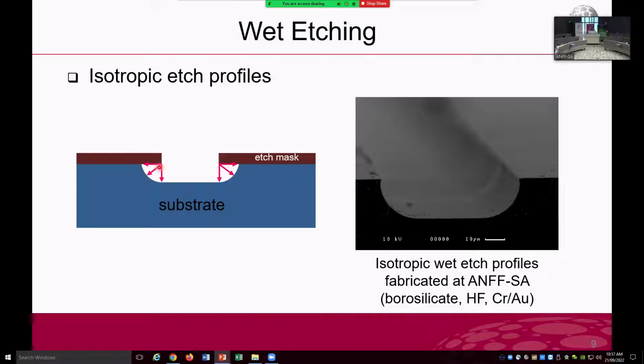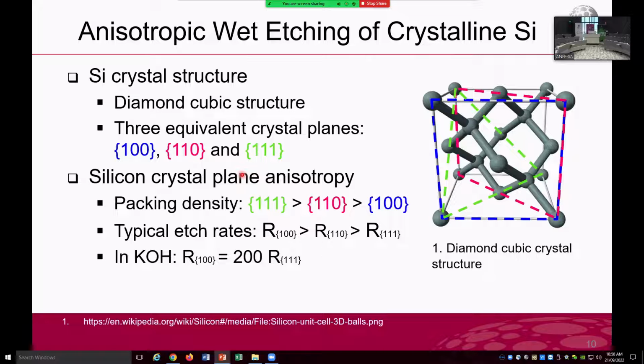As you see, in isotropic wet etching, the etch front proceeds as a spherical wave, so etch rates are equal in all directions, horizontal and vertical. And that's the reason we end up having these round etch profiles. And then the maximum aspect ratio is 1 to 2, I would say.